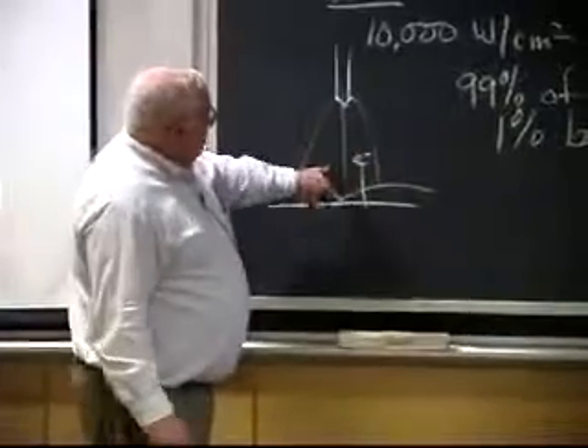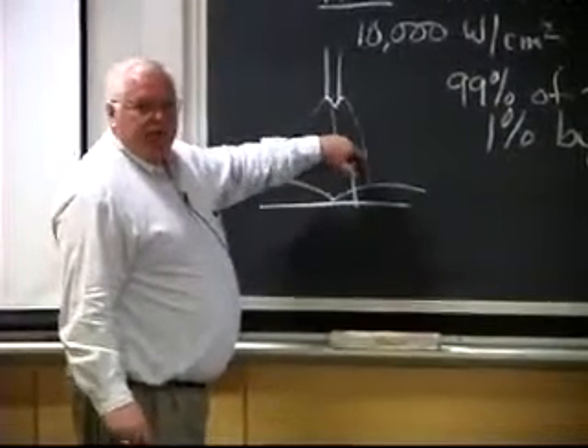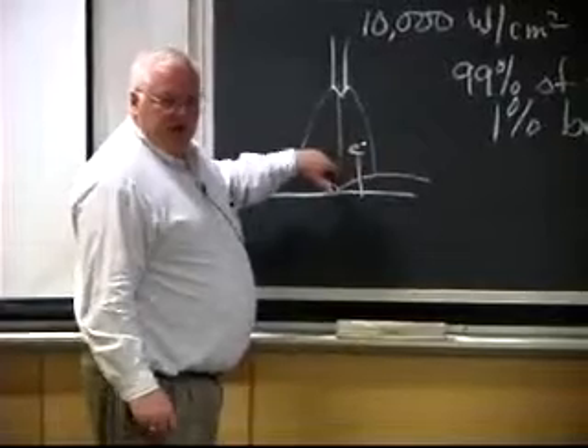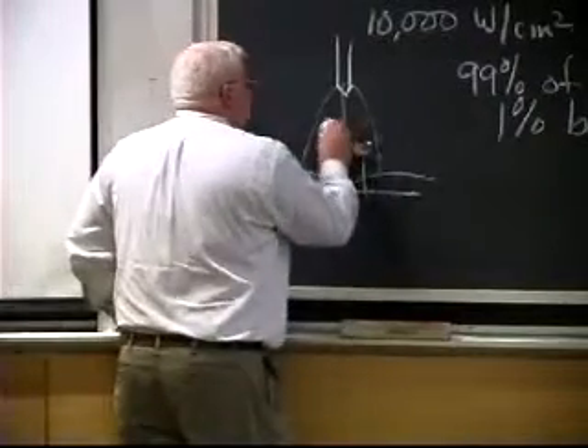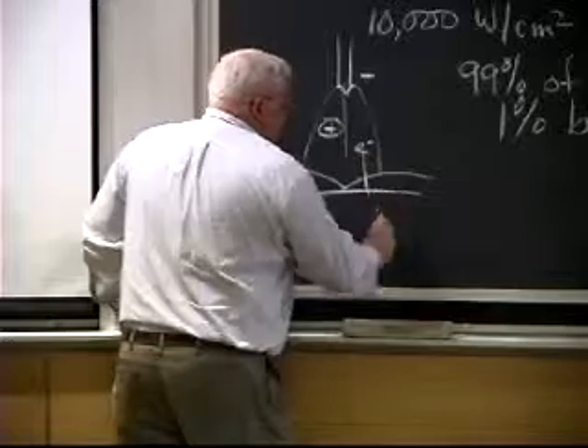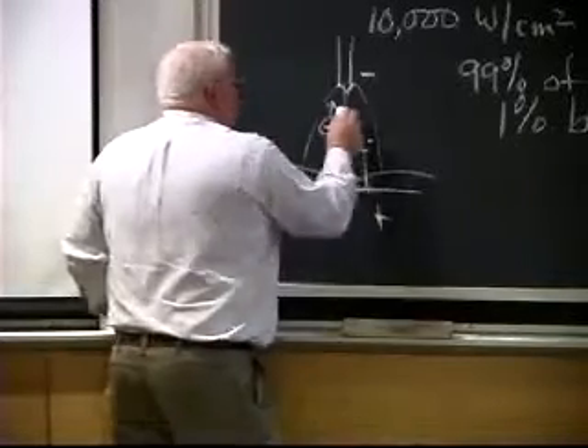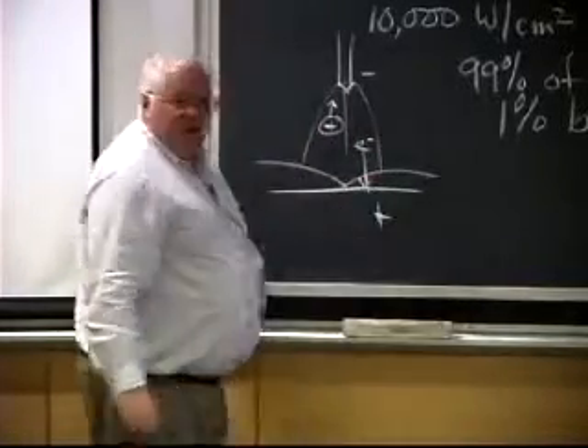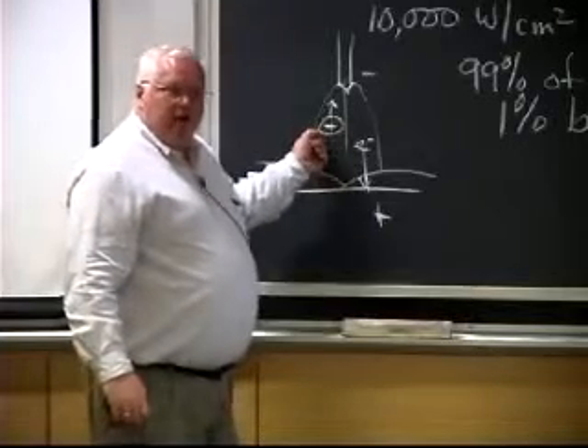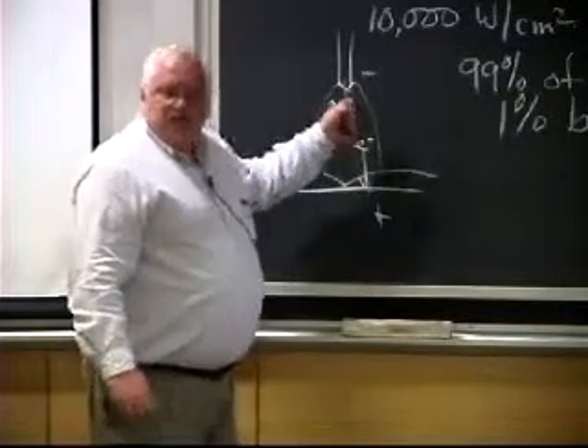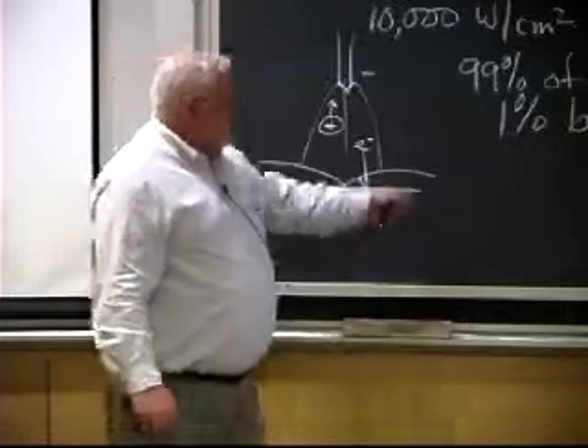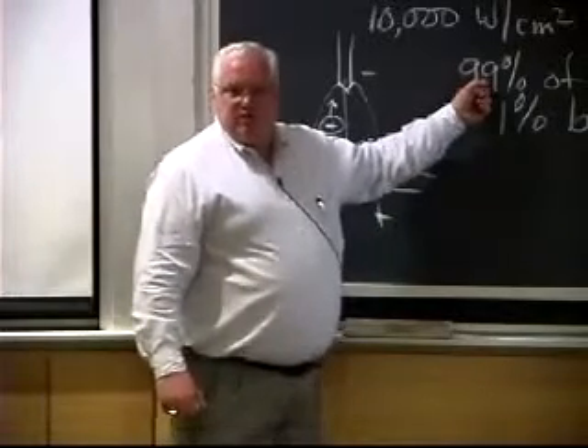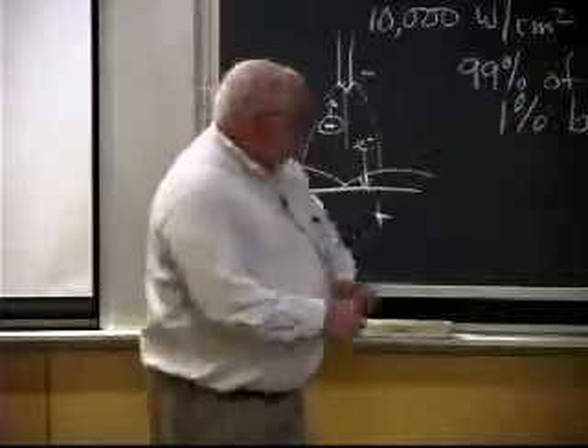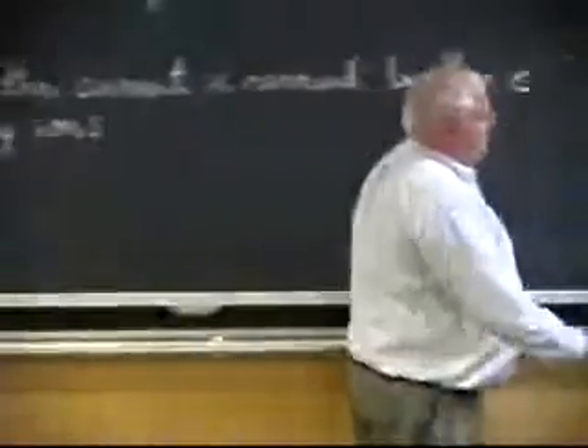So, in any case, whether you consider a plasma a fourth state of matter or not, basically you take a neutral gas and you separate it into positive and negative charges. And so I have positive ions. If this is the negative electrode and this is the positive electrode down here, the positive ions are going to go that way, the electrons are going to go this way. However, the electrons have about 100 times the mobility of the ions because they're nice and light. So they move much faster, about 100 times as fast, which means that 99% of the current is carried by the faster moving electrons and only 1% by the ions. Now, see, I did prepare a lecture. I couldn't have done that if I hadn't prepared it.